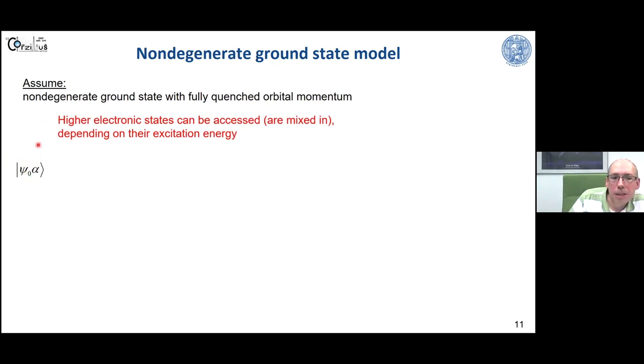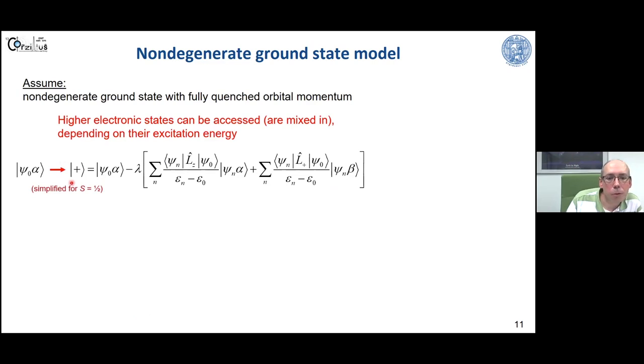But now there are always higher electronic states, and if they are accessible because their energy is rather low above the ground state, then they are mixed in, and we have a mixed basis set, and this depends on the excitation energy. Then we have to make a linear combination. We have to mix in an excited electronic wave function, psi n, which is the nth excited state. And here we have the difference of the energy of this excited state above the ground state. You can also see that we not only mix in the alpha spin state, but also the beta spin state. So this causes a mixing of the two spin states in this new basis set. And this is just caused by spin orbit coupling, because here you can see the spin orbit coupling constant again.